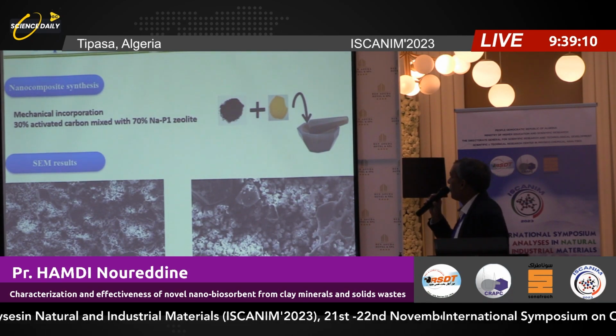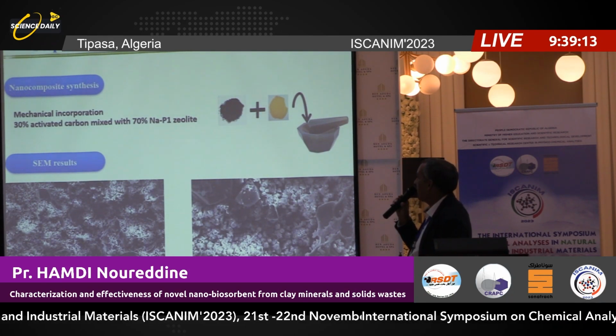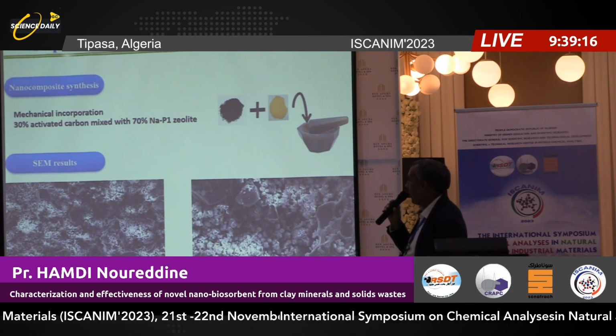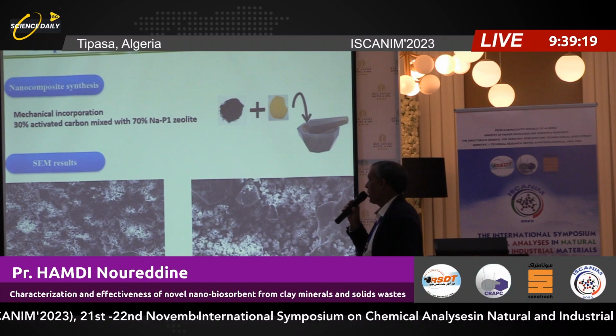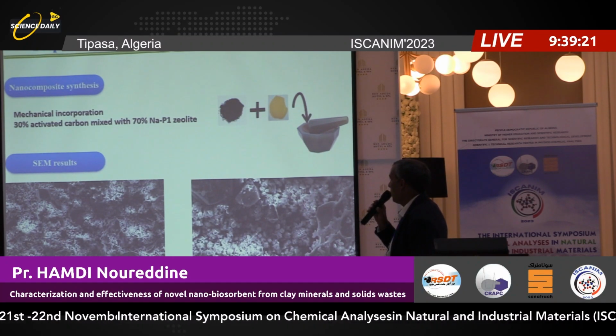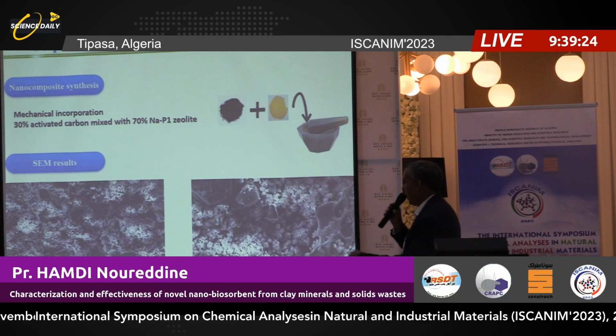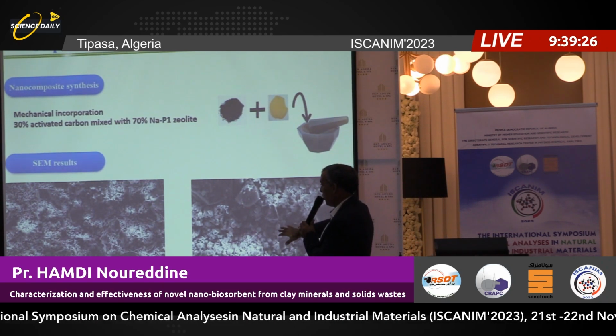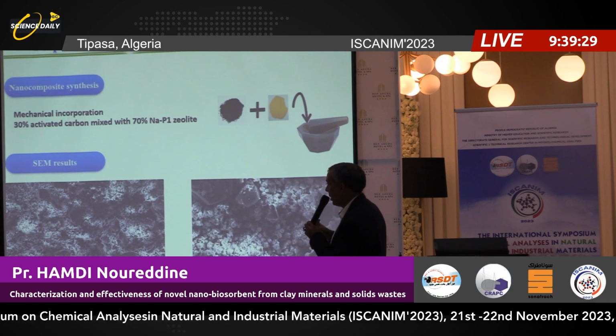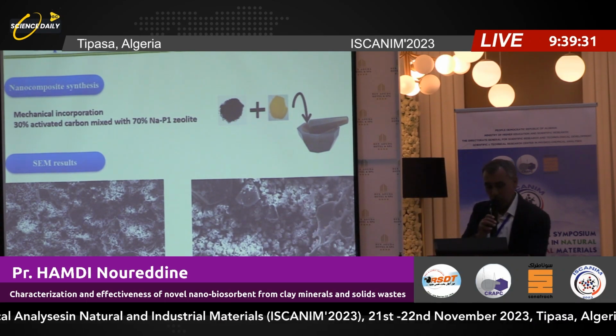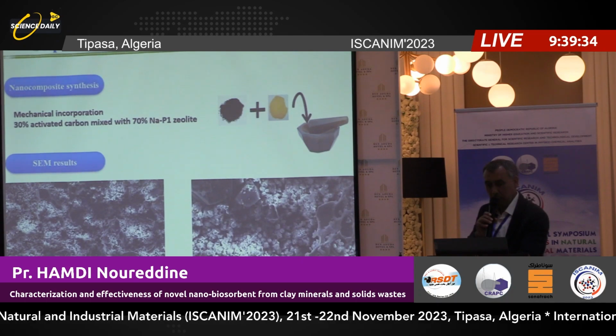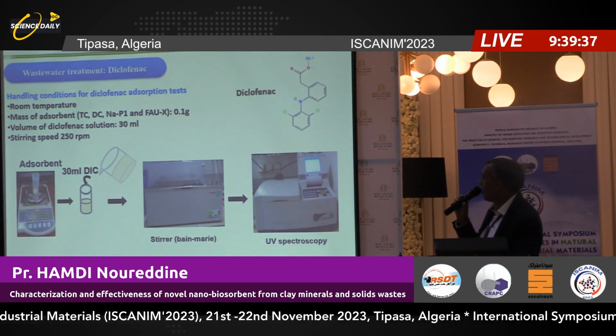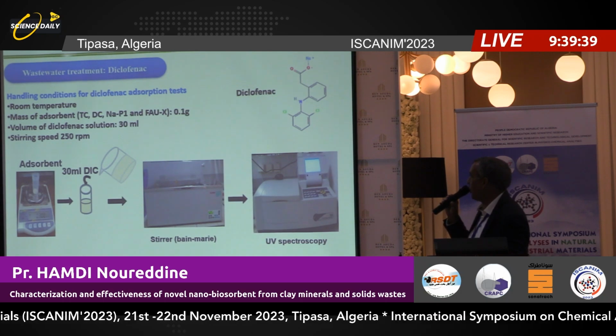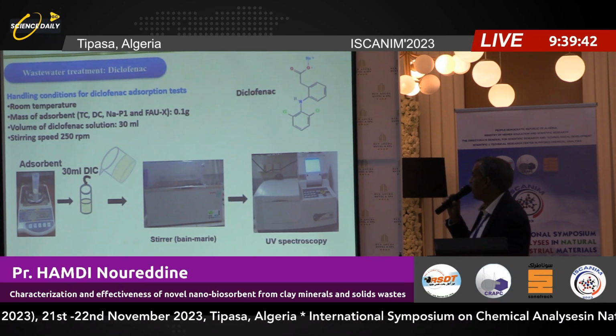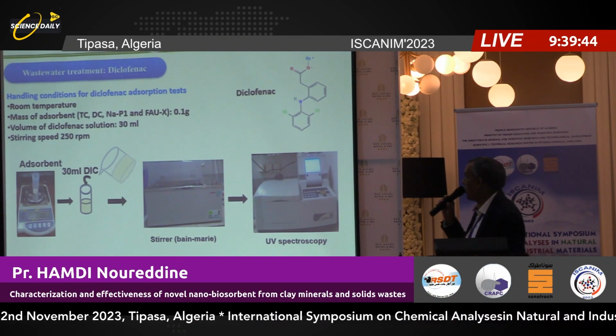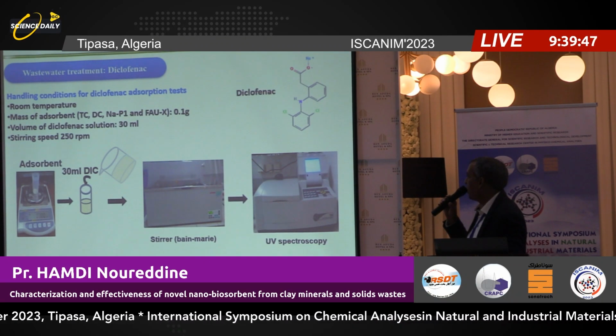Now, the preparation of our composite zeolite activated carbon by simple mechanical incorporation of 30% of activated carbon with 70% of zeolite P. As you can see here in the scanning electron microscope, we put the activated carbon in the porosity in order to react with the pollutant when we adsorb any pollutant used. The adsorbate here is diclofenac. Diclofenac is an anti-inflammatory medicament. It was very used in the period of COVID-19.